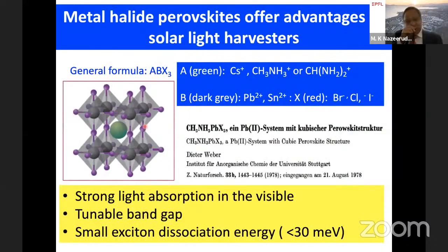So what is perovskite actually? Perovskite materials are very simple, a salt type of material, having a typical formula of ABX3. A is a monocation, B is a dication. The monocation can be inorganic or organic. And the dications are metals, that's lead 2+ or tin 2+. But lead 2+ is the efficient one because of the heavy atom effect. And the halides can be bromides, chlorides, or iodides. If you look at the band gap of these materials, iodide has the smallest band gap compared to bromide, and bromide has a smaller band gap compared to chloride.